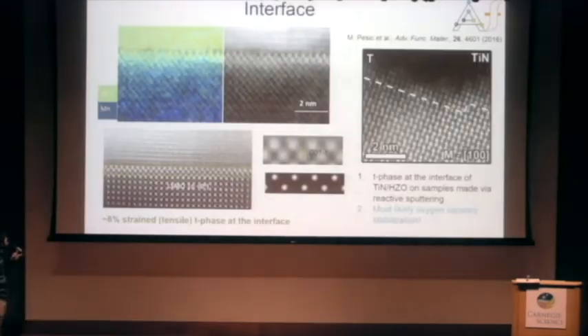Okay, so finally, let me talk about the interface. These are the chemical maps, and we see that at the interface between LSMO and HZO, we have a different phase of HZO itself, and that is in fact a tetragonal phase, a T phase, which grows in the 001 direction, but it is completely epitaxially strained with respect to the substrate. So there is an 8% tensile strain T phase, which extends for 2 to 3 monolayers.